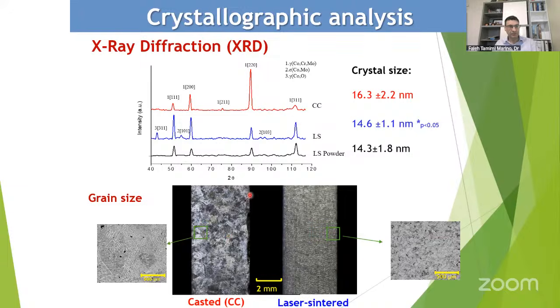So you can see that, and we do the same thing for laser sintered metal. You can see here that in the cast, the grains are very obvious. You can see grains of metal. They have different colors, right? Each one of these shapes over here is a grain of metal. They're very big. In laser sintering, when you do the same experiment, the grains are tiny. Because we are hitting very thin layers of powder every time, basically the size of the grains of the metal is the thickness of the layer of powder that you're adding. So they're very small. These ones could be close to 1 millimeter in size. These ones are microns in size.